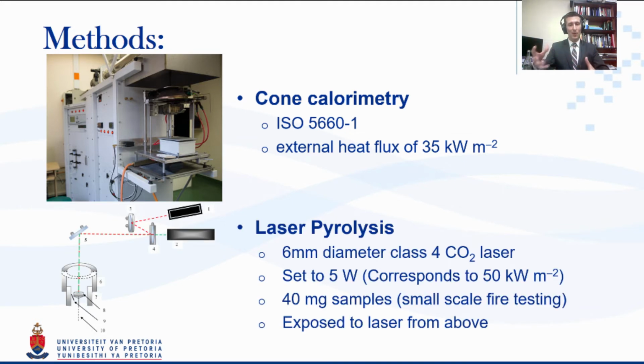Our other method that we identified, which was one that people in our group invented, was to do a TGA coupled laser pyrolysis, which basically boils down to this: we can use extremely small samples, similar to those that one can usually analyze in analytical equipment, of 40 milligrams, and we can get an indication, on a small scale, of what sort of charring, barrier effect, or mass loss effects occur, which gives a very good indication of some of what one can expect in the larger scale tests such as cone calorimetry or open flame tests.